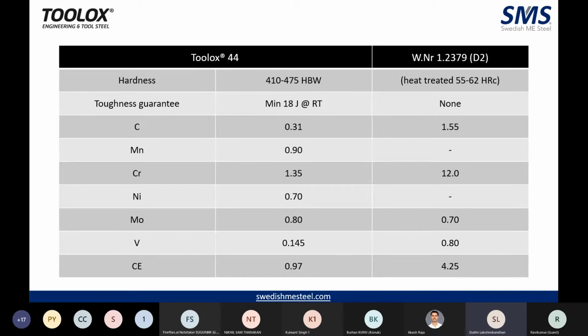And at the end, you will find the CE values pronounced as 0.97 and 4.25 for D2, which denotes that the thermal cutting and welding of the material is very good for Toolox, and that's not so the case for D2.